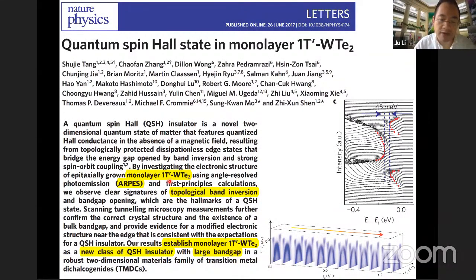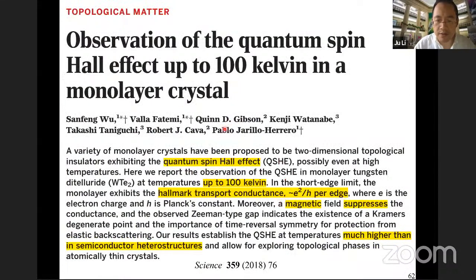We predicted it has to be a monolayer. If it's a bilayer, it wouldn't work. It would be a normal insulator. And then later at MIT, Professor Pablo have shown that the edge conductance is this perfect e square over h quantum conductance. And furthermore, this has a very interesting magnetic field dependence because there is a spin orbit locking, and this persists up to 100 Kelvin. And later, they've also found that this monolayer tungsten ditelluride is also a superconductor. So this opens a possibility for this topological quantum computing as well.